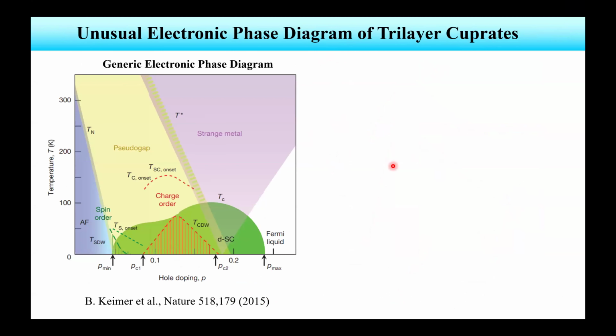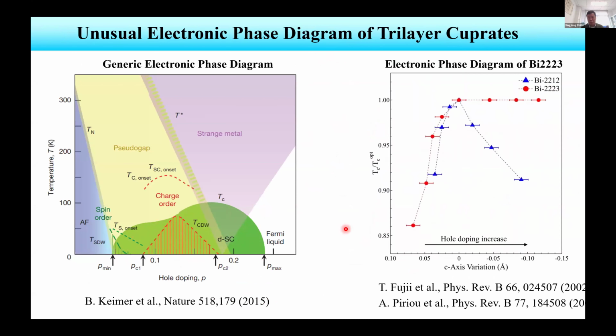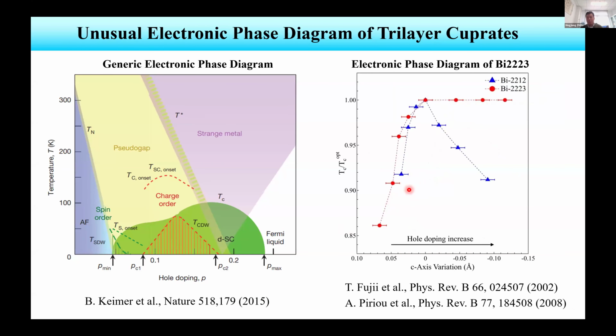And also, as you already know, usually TC depends sensitively on the doping. It goes up first, then goes down again. It forms a dome-shaped phase diagram. But in three-layer systems, it's different. Like in bismuth 2223, you can see that TC goes up first with increasing doping, reaches the maximum at the optimum doping, but it stays almost constant in the overdoped region. So this phase diagram is of course different from the usual phase diagram we can see.